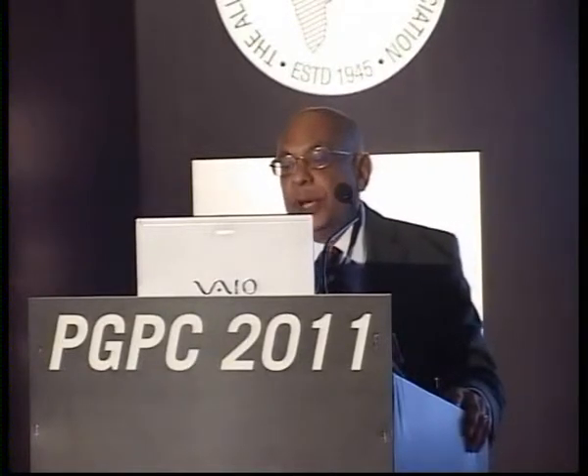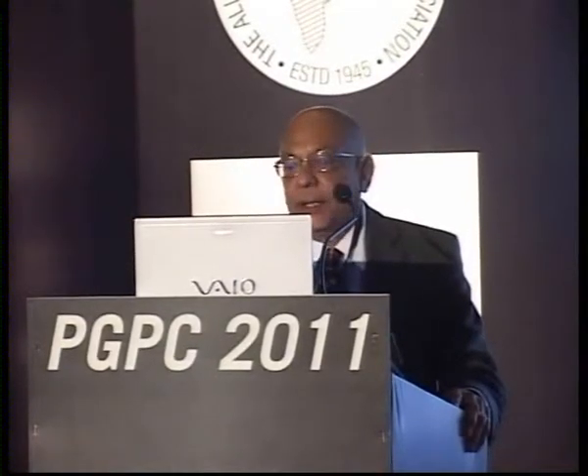Fiber length, and some of the speakers this morning also discussed that. I think it plays a very important role. What you have on the blue side is the stiffness. This is a short glass fiber. Stiffness meaning the rigidity, the flex modulus is an indicator. Then the strength, the flexural strength and the tensile strength, you can derive much better with the long fibers. And of course, the continuous roving gives a very good impact stiffness balance.